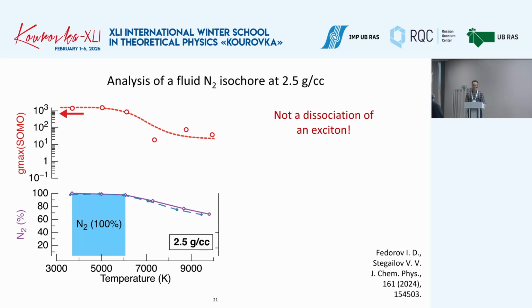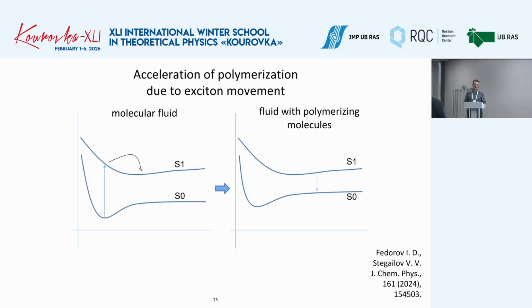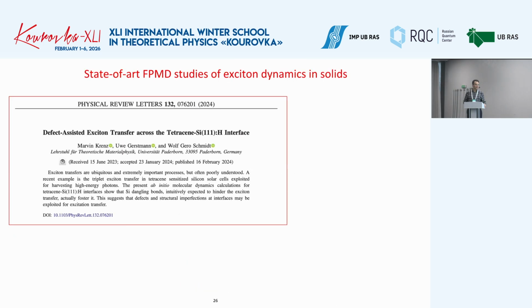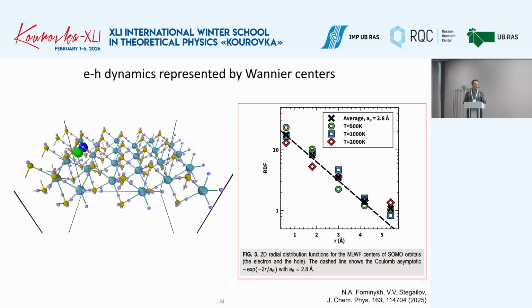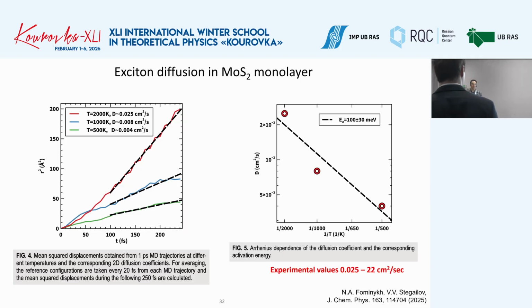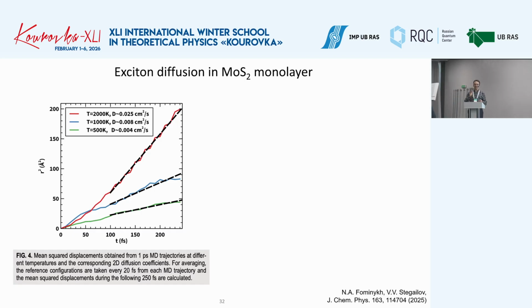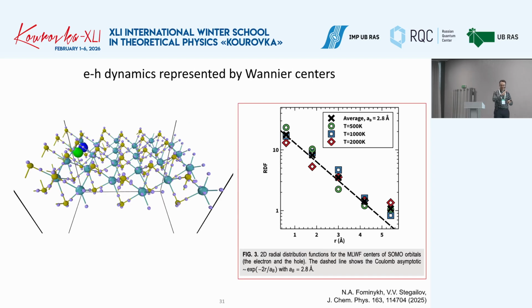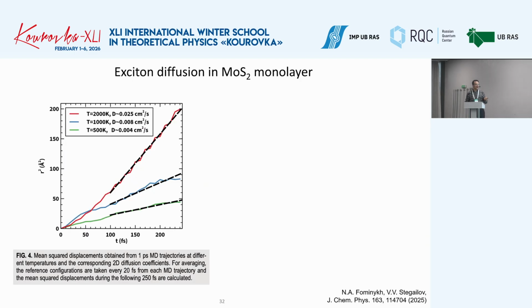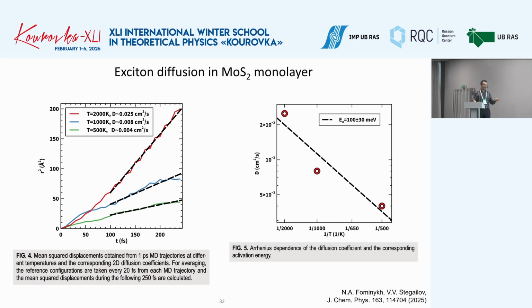Okay, I also have one short question concerning the last part of your talk where you showed diffusion coefficients. Seems they're too small. Or it means that your sample is quite dirty, because typically diffusion coefficients should be 1, 2, 3 centimeters squared per second. It seems to be like a hopping regime, not diffusion. Our samples are the cleanest possible samples in the universe, because it's a model. Okay, then the diffusion coefficient should be 10 times larger, maybe 100 times. It should be 2.5 centimeters squared per second.